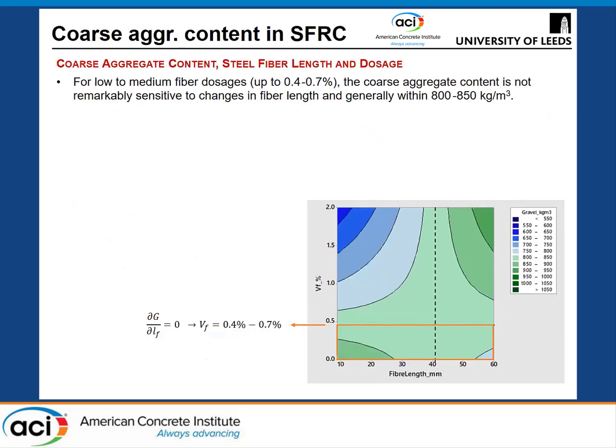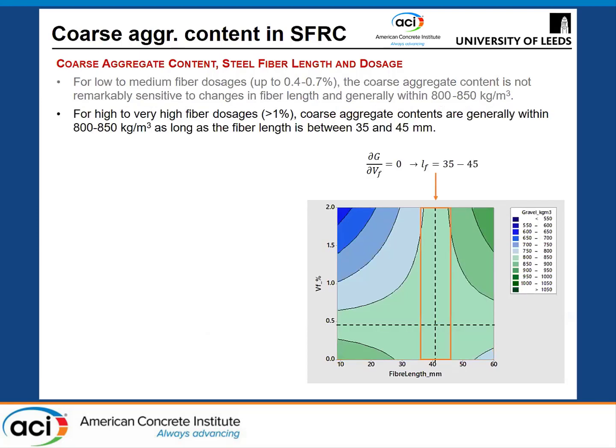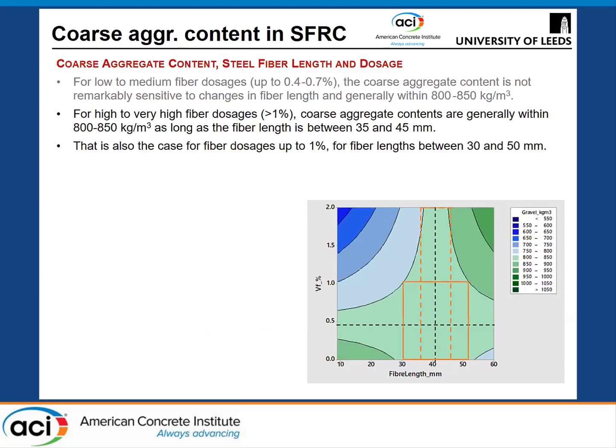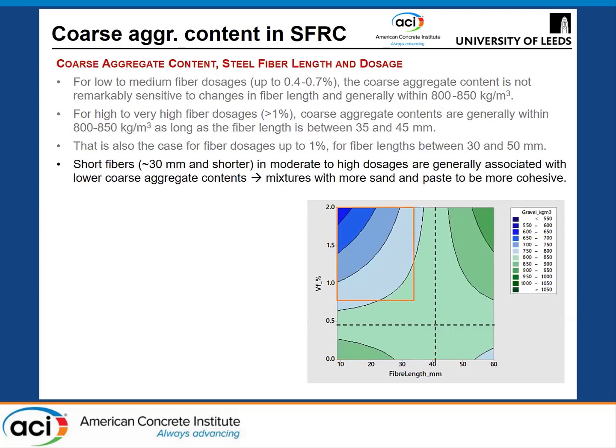And with this model, you can obtain, for example, very interesting plots like this, where you can see a little bit the trends that each, for example, this shows the coarse aggregate content depending on the fiber volume fraction and the fiber length. So there's different, I'm going to skip this part because I don't want to spend a lot of time, but there's different conclusions that you can obtain by looking at these contour plots. And again, this is related to the interpretability.